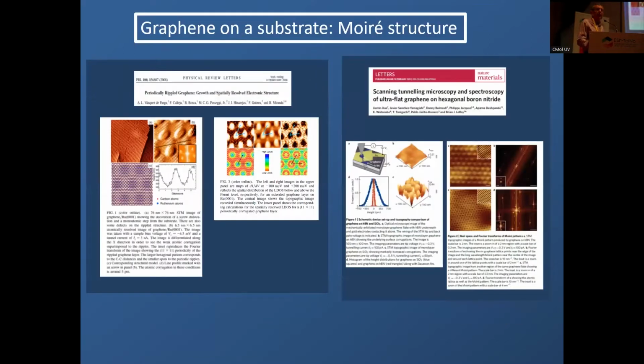People started to play with boron nitride and graphene after this interesting discovery. These are old papers. The thing is that the lattice constants of graphene and boron nitride are close, but they differ by only 2%. And because of that, you create large moire patterns where the unit cell is on the order of 10 nanometers or more. And they are like metacrystals, larger crystals.